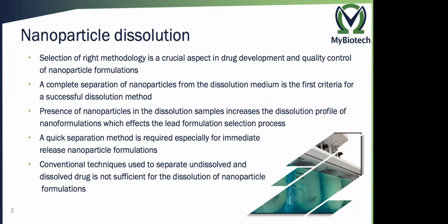Another important point: why do we make nanoparticles? Because they have a higher dissolution rate, which means they dissolve quickly. So I also need a quick separation method, especially for immediate release nanoparticles. The reason is quite clear. If my sampling procedure takes 45 minutes because I need to separate the nanoparticles from the dissolution medium using ultracentrifugation, but I take the sample after 3 minutes, the result I read at the end of the day is not the 3-minute dissolution result, it is the 45-minute dissolution result.